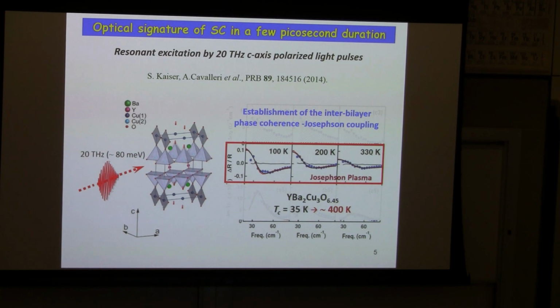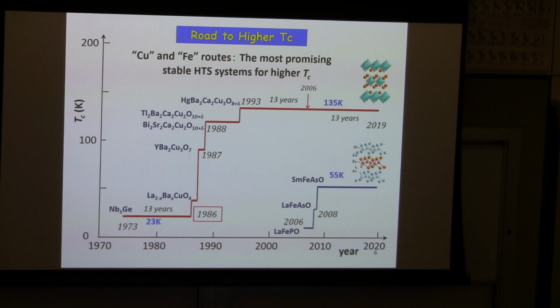This is YBCO. When the YBCO material is pumped by a laser pulse, then within a period of a few picoseconds, there appear some evidences for Josephson coupling between the copper-oxygen layers that persist up to well over 300 K. So in that sense, this is a room temperature superconductor, realized only for a picosecond duration. But this is not practically so important. Practically important is a stable superconductor, and the record has been stagnant for over 26 years.